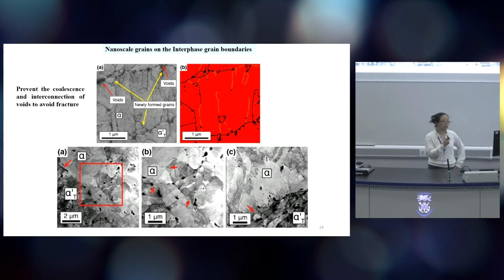This characteristic is important for irradiated steels, because under irradiation we will induce voids and defects on the grain boundary, which will cause failure, and the nanograins can delay the failure from occurring.